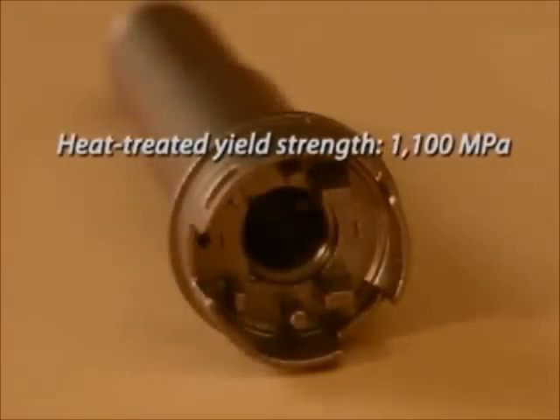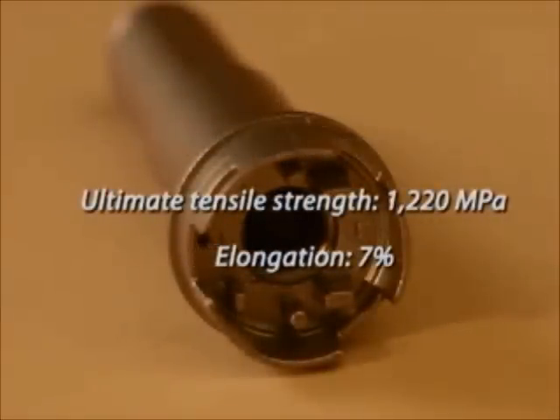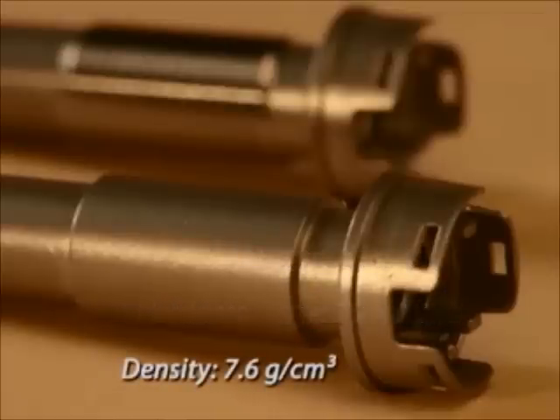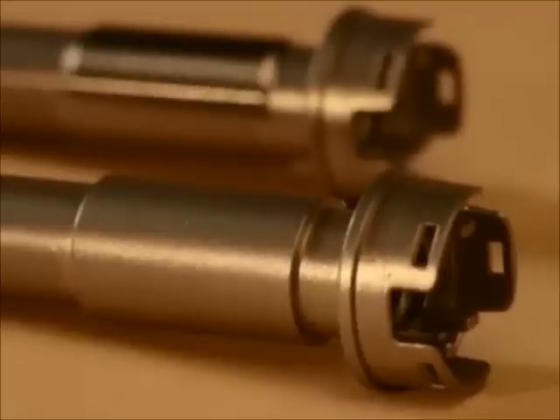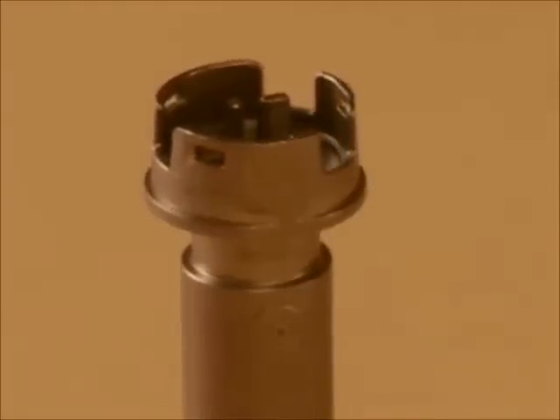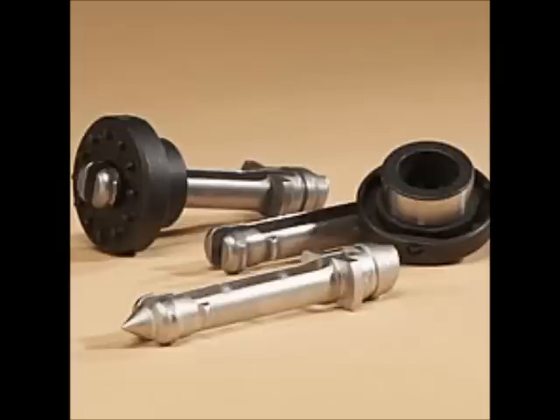The length of the threaded port creates complexity, as do the thin walls and fragile features, and the stringent customer requirements on visual aspects add to the difficulty of fabrication. The parts are formed close to net shape, with only coining and passivation required on all three, plus CNC thread cutting on the port only. This new application is estimated to save the customer 50% over the cost of fabrication using alternate technologies.